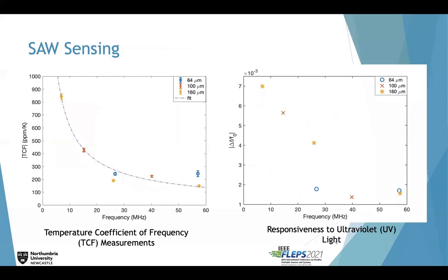We have used the fabricated devices to monitor the responses to temperature change, and also when they're exposed to UV light. On the left-hand side, you can see the temperature coefficient of frequency measurements, which means that we monitor the change in frequency with respect to a reference frequency when the temperature was changing. So this can be crucial when maintaining a constant temperature is very important for the operation of the device. And we could observe that the devices that had higher wavelengths when they were calibrated at their lower frequency mode showed a more significant result to the temperature change.